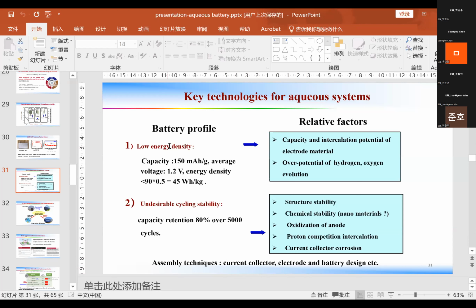For the specific energy, we must find some way forward because the potential window is still low, and another problem is that we must increase the overpotential of hydrogen and oxygen evolution, because in practical batteries the water decomposition must be avoided. Otherwise, the electrolyte will be consumed. This is the main failure mechanism of aqueous electrolytes.